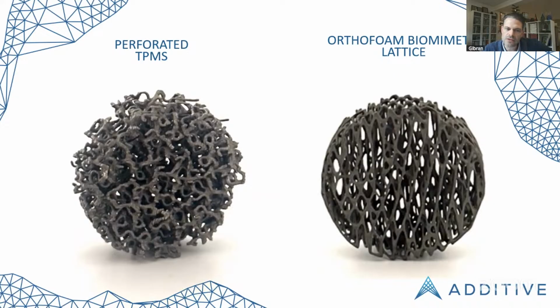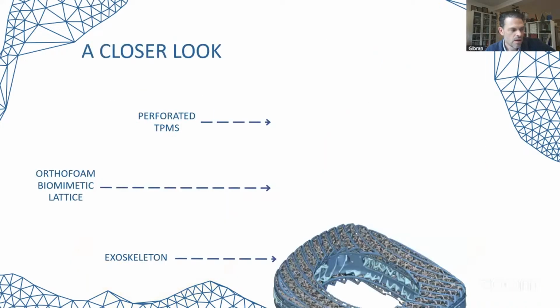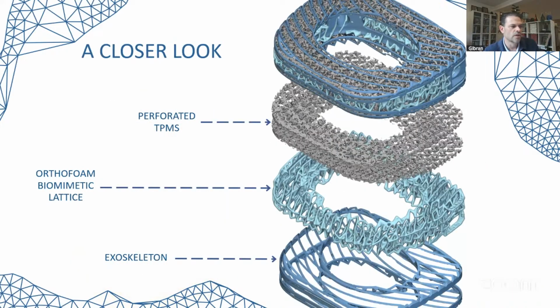So the idea is that the perforated TPMS, and the testing that we've done shows this, helps to get that initial adhesion right on the end plates. It grips right on there. Then the orthofoam lattice in the middle really helps to distribute the load more evenly across the two end plates to try and address stress shielding and point loading. So when we put that into a spine cage all in one, this is kind of what it looks like. So you can see up the top what the final implant looks like. Then you can see the gray area is the perforated TPMS, which adheres to the end plates very well. Then the orthofoam biomimetic lattice helps to distribute the load evenly throughout the entire interbody device. And then an exoskeleton helps to basically hold everything together.